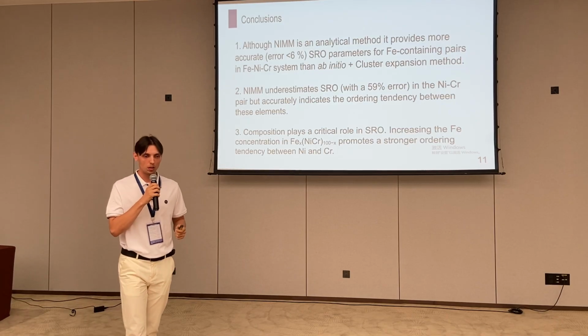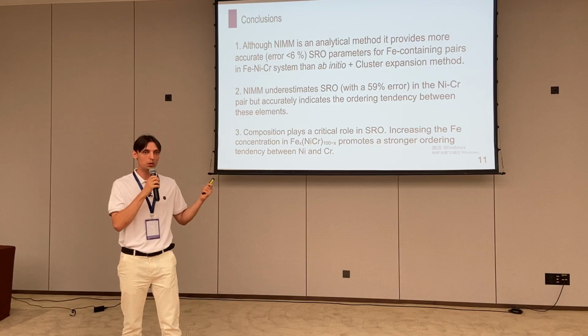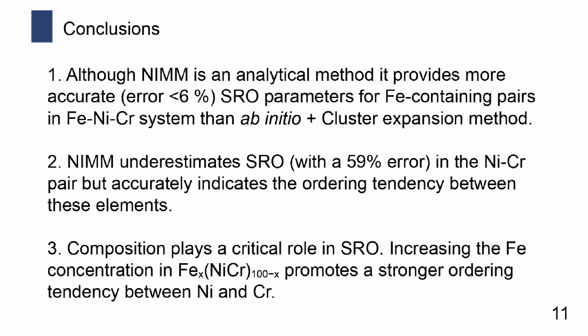So to conclude, the method provided in this presentation has promise to screen a vast compositional space of high-entropy and medium-entropy alloys. It allows accurate prediction of the weak interactions between iron-nickel and iron-chromium in the iron-nickel-chromium alloy, and most interestingly, it can show that increasing iron content in this system influences the ordering between the nickel and chromium pair. This is just the beginning of my future work, which will be used as a basis for postdoctoral research in the future.